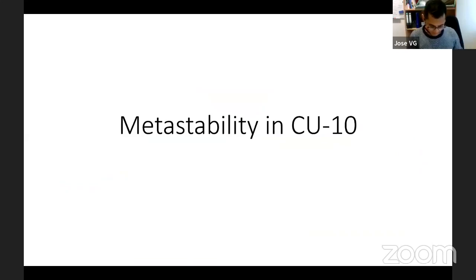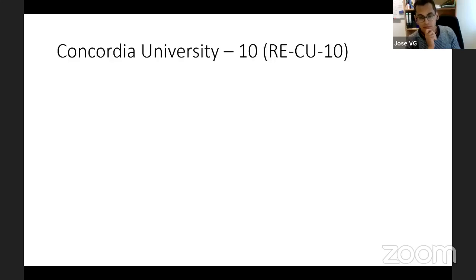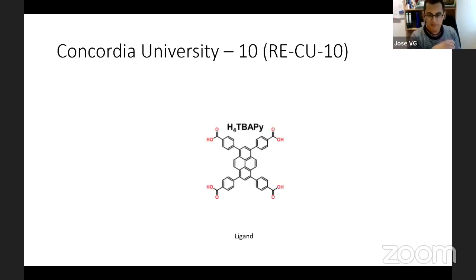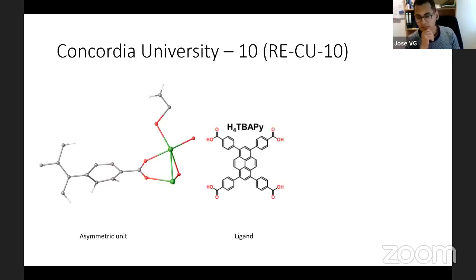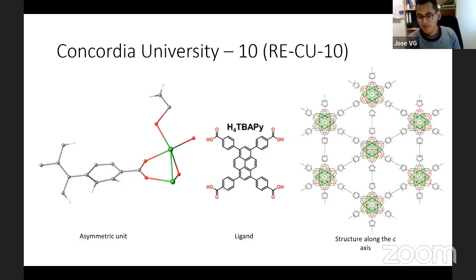We tried to use the photocrystallographic technique also for another MOF called CU10, which means Concordia University number 10. Usually it's made with a rare earth metal. This is the ligand. This is the asymmetric unit. And this is the overall structure along the c axis. And as you see, this material has very long spaces between the metal clusters. So these have even larger pores than HKUST-1.